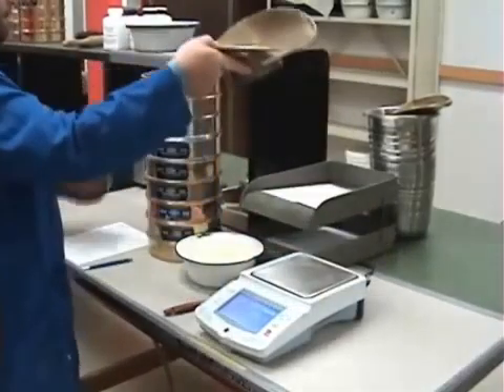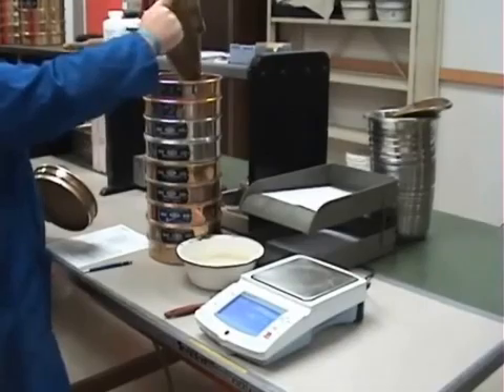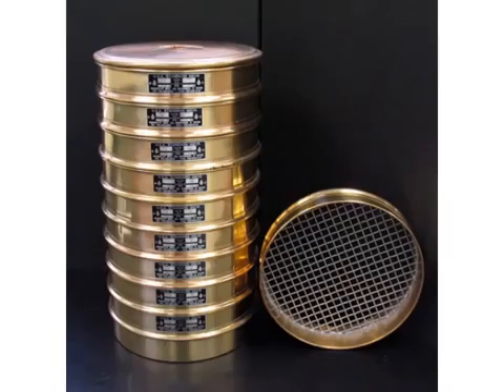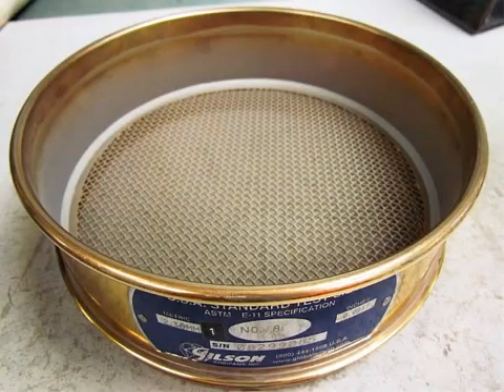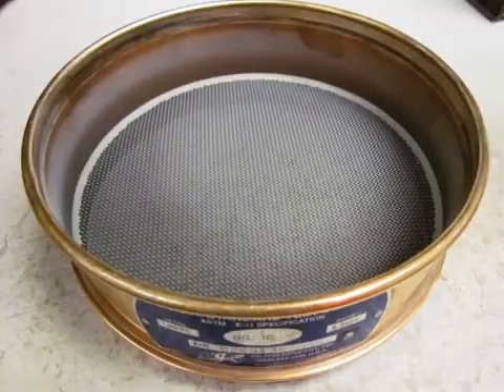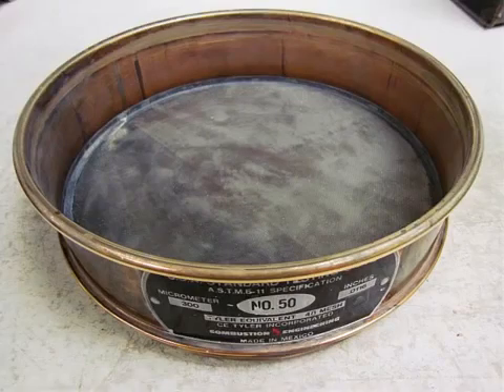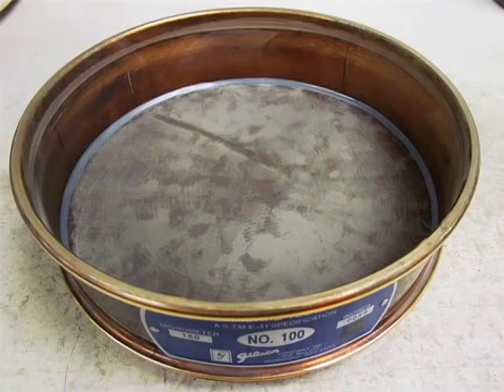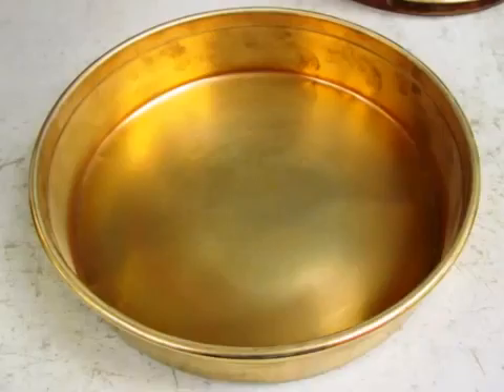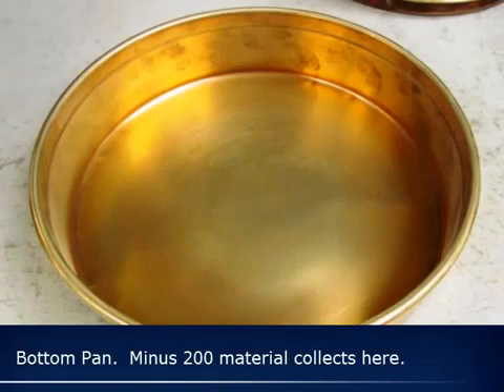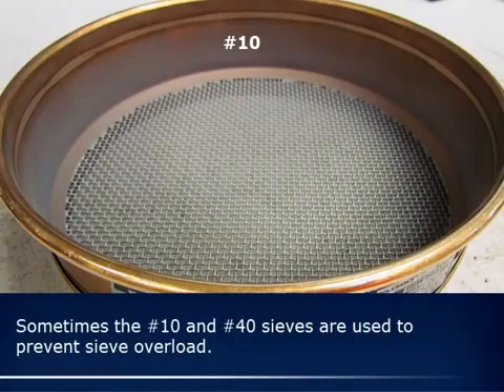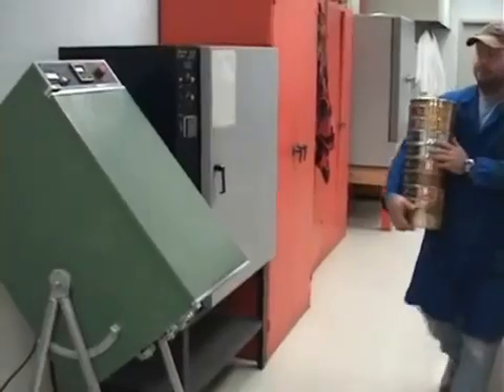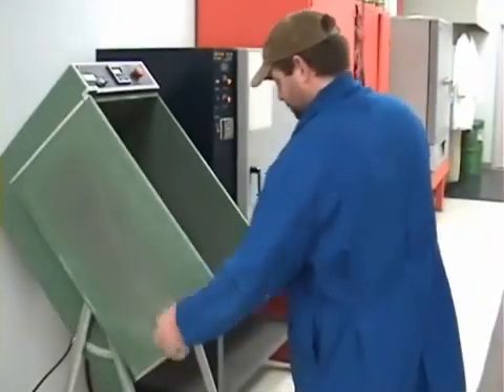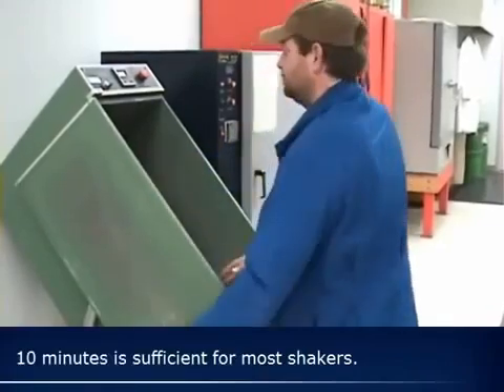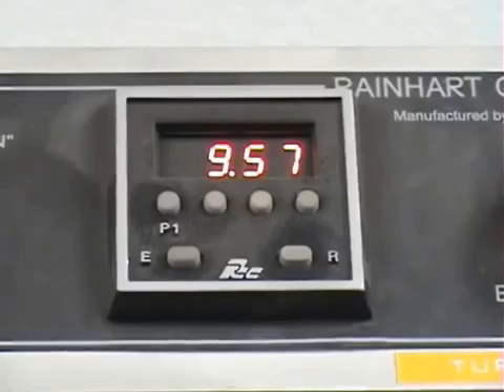Take the material and introduce it into your nest of sieves. Your nest of sieves usually consists of the number 8, 16, 30, 50, 100, and 200 sieves, and the bottom pan, which is your minus 200 material. Next, cover the nest of sieves and put into the shaker. Shake the sieves for 10 minutes.